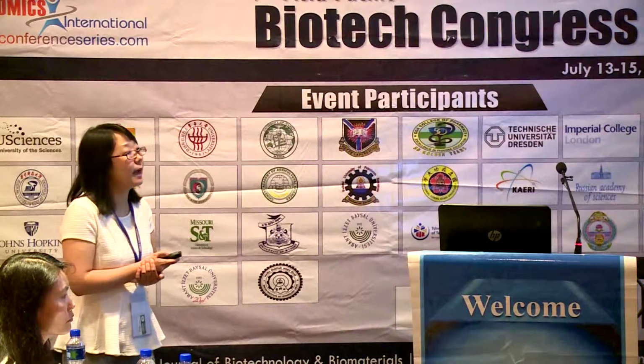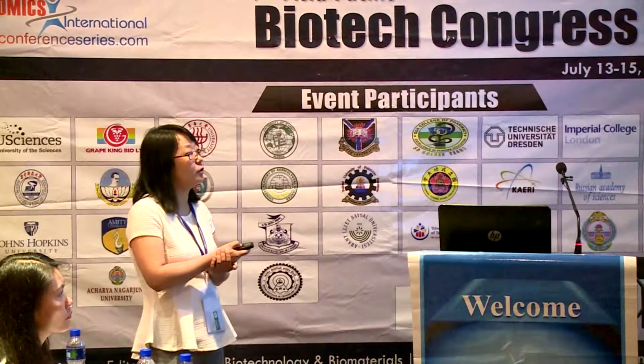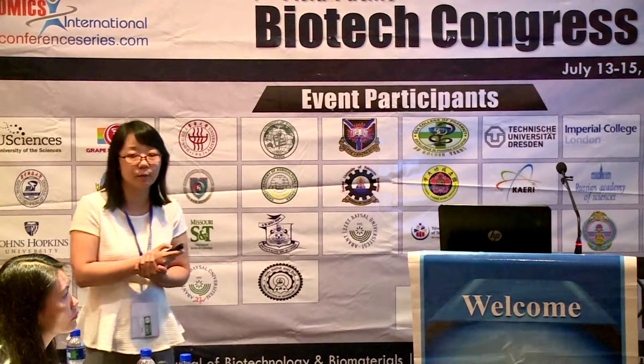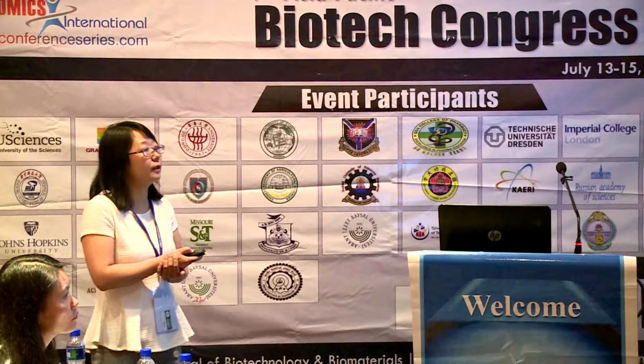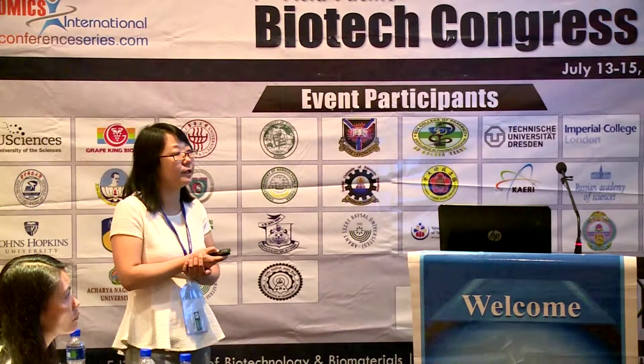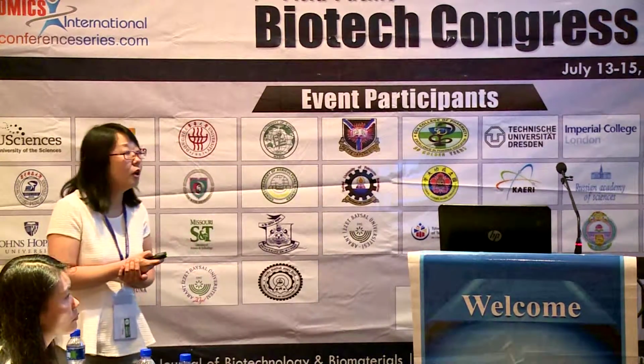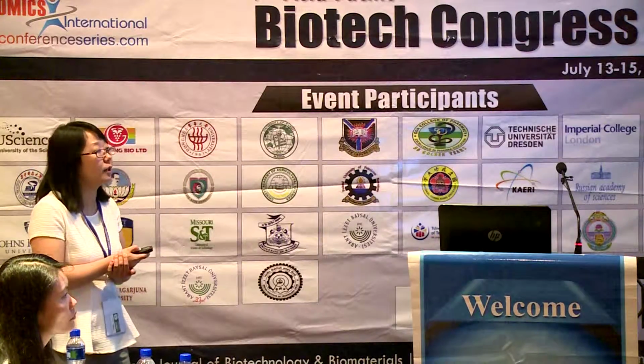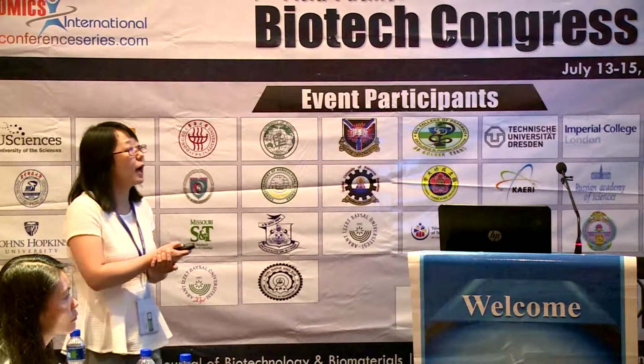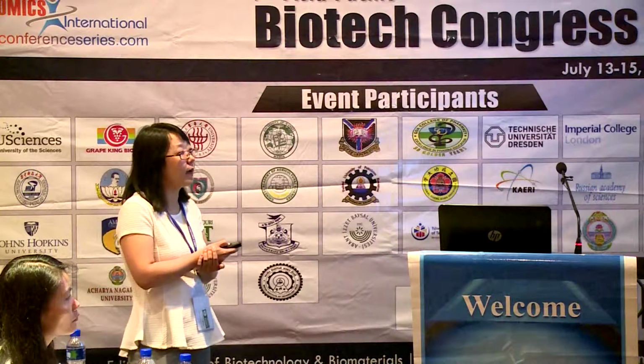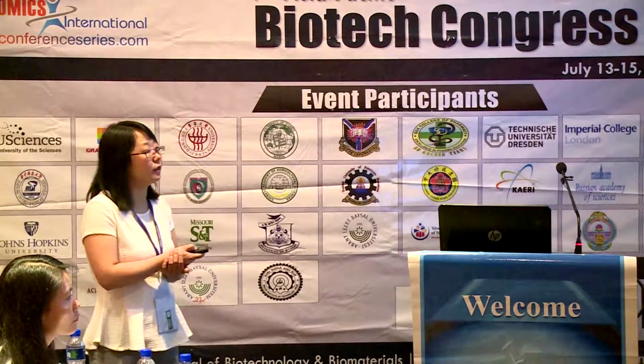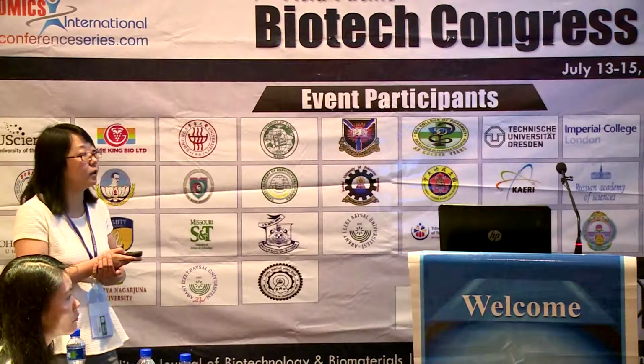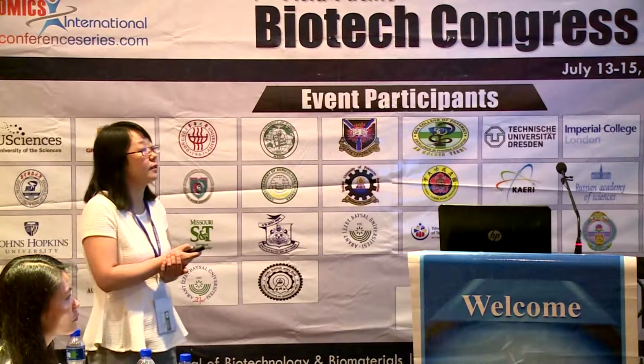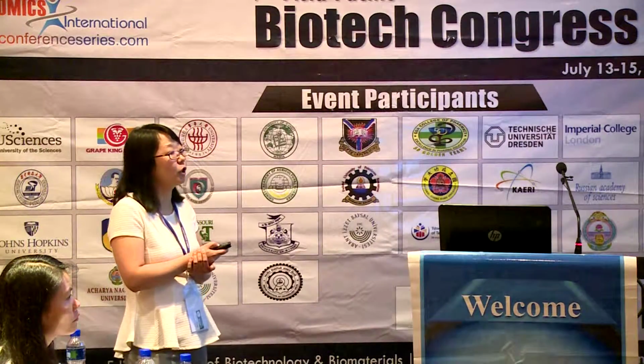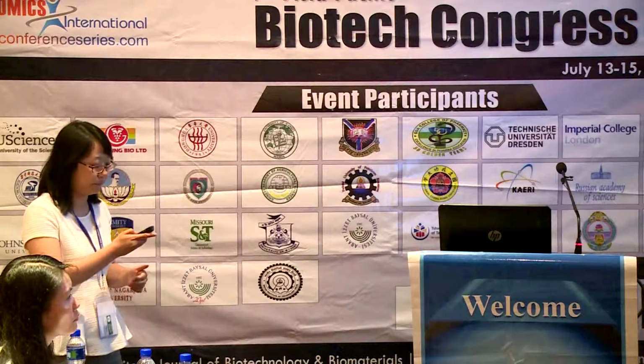To prove this idea, I want to successfully use the half tube to capture another polymer inside. We know the cavity of the 6-helix bundle is around 2 nanometers, so it is a good candidate to capture another DNA duplex. So I held a 7th DNA duplex in the half tube, then used a sticky-end cohesion to capture it inside of it. Please note there is just a single sticky-end cohesion, so it is much more flexible.